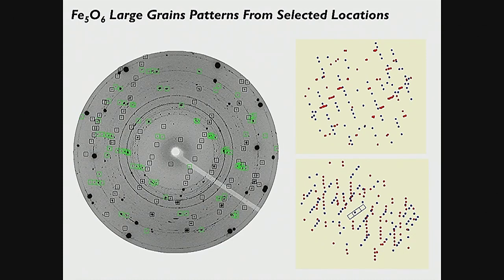This is a very clean pattern by my standard. It still has two large grains of the phase I'm looking at. It has the largest spots there. They are diamond diffraction peaks. You have the powder rings of the standards, and you have some other grains in there. Still, I managed to sort out these things and nail down the structure of a new iron oxide.